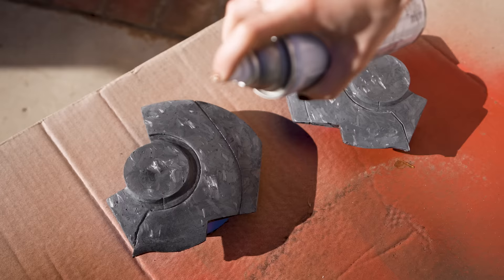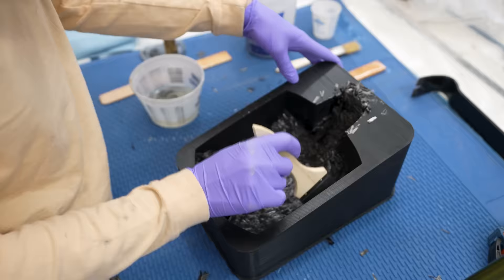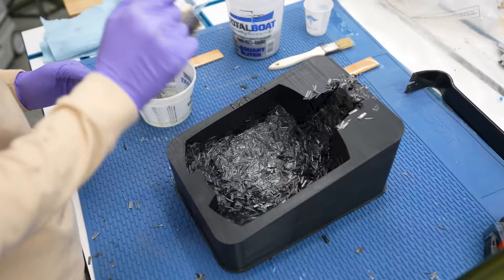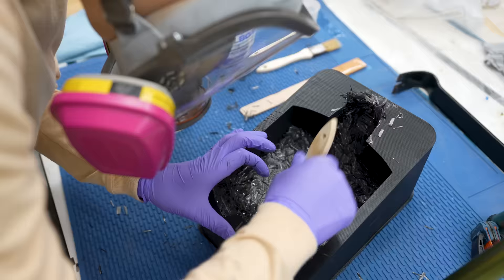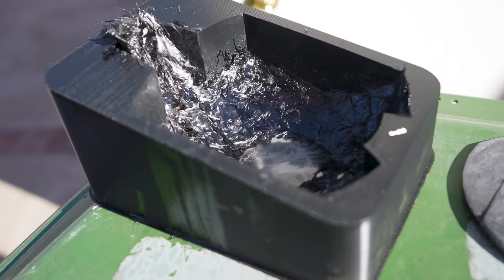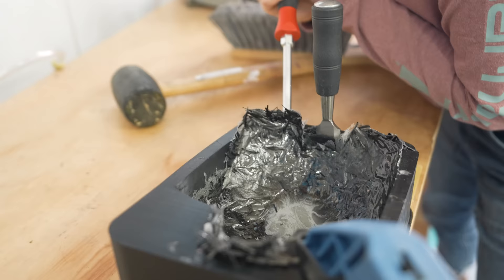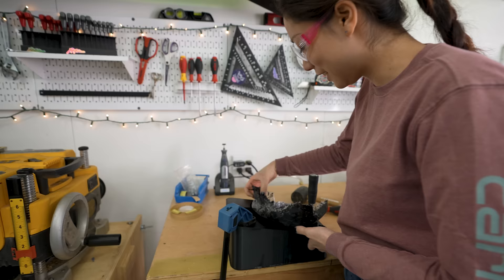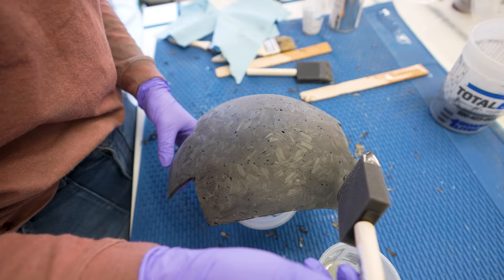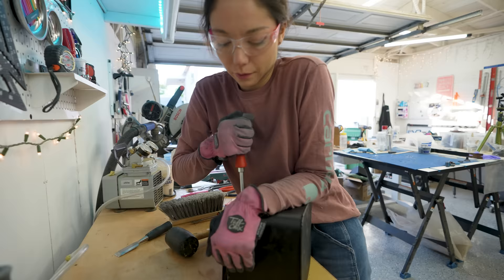I do want to point out that the side panels were the only ones in this project I didn't do a flood coat of epoxy on and I regret it a lot. I think the air pockets and puckering are really distracting, and I wish I could go back and fill it in, but by the time I decided I needed to do that, I had run out of time. For the top helmet portion, I skipped the vacuum bag altogether and wanted to see if I could pull off a standard wet layup with forged carbon instead of cloth — and the answer was yes. I actually think it came out a little better than the vacuum-bagged parts. The key was that the first coat of resin needed to be super, super thick and you have to do a really good job of stippling the fibers on. The brush hitting the fibers vertically helps. You paint on the thick coat of epoxy, let the fibers sit on top for a bit and soak in on their own before going in with the brush. It kind of behaves like felting — once the fibers start matting together, it holds its shape really well.